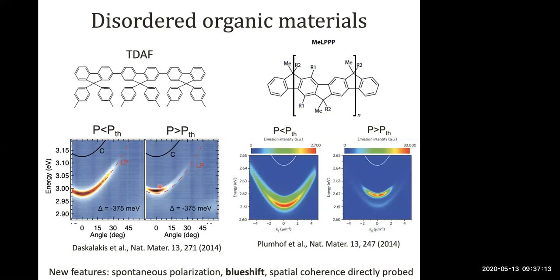Okay, great. So this material here was thermally evaporated. MeLPPP, which is a ladder polymer, was spin coated in very similar physics. So you see this collapse in K space, a blue shift as well, as you cross threshold. And this blue shift is a signature that you have some type of interaction. And as Joel just mentioned, in the case of these materials, that interaction is coming from the fact that you have a ground state bleach.